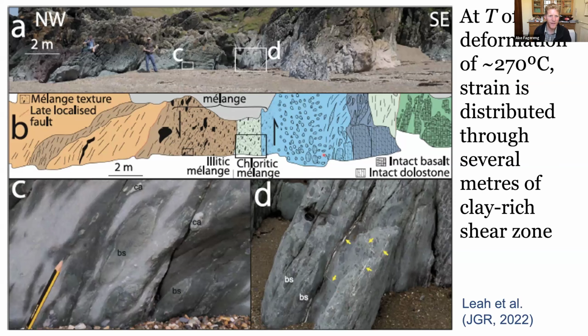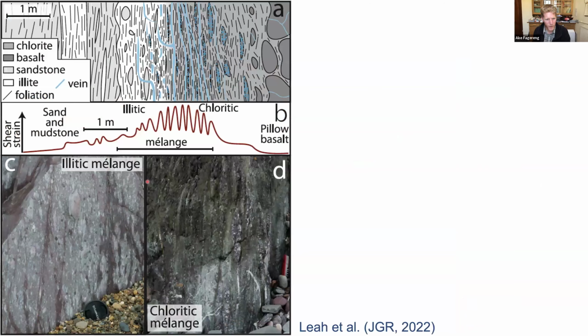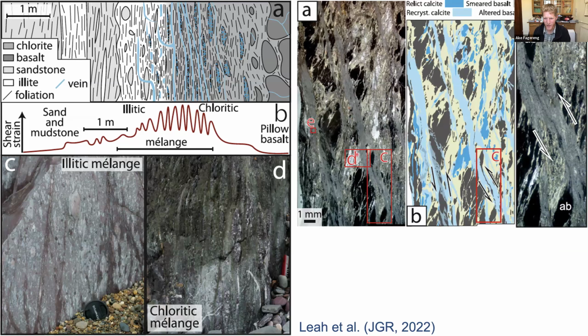So if we look at a fault like that, what we see it localizing into, in this case, we have basalt on the right. That's relatively intact or low strain. We have low strain carbonates, then very high strain chloritic melange and illitic melange, and then relatively low strain sandstones. And if we look at that margin in detail, basically the same idea as I just said. We have strain localizing into these more clay-rich, lower friction rocks near this boundary. If you look at it in thin section, it has localized carbonate veins that are then subsequently sheared, which gave us an opportunity to try and get at what the stress level was.